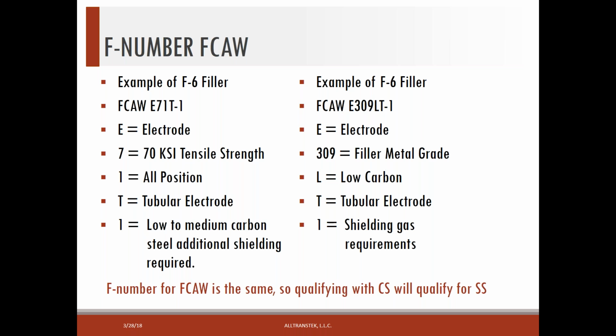And then if I take a weld test on E71T1, since 309L, which is again what you commonly use for welding stainless to carbon, or if you use 308LT1, it's an F6. So you don't have to qualify welders on stainless as long as the F number is the same.